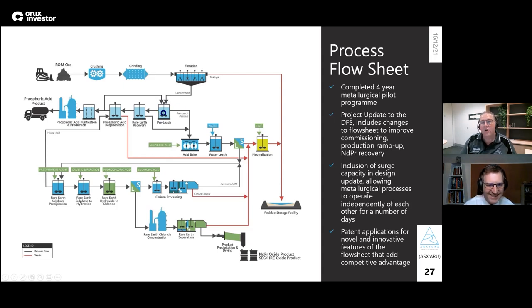So we then leach that concentrate in phosphoric acid under controlled conditions, getting the temperature right to keep various things in solution and keep various things out of solution. We then separate after that. We take the solids and then we heat it up, and the solids that precipitate out from heating it up take all our rare earths through to the bake. We then regenerate the phosphoric acid with sulfuric acid to produce our phosphoric acid for leaching, but also an excess phos acid, which we clean up for impurities, take away some water, and then ship out to Darwin, and then over, most likely to India.